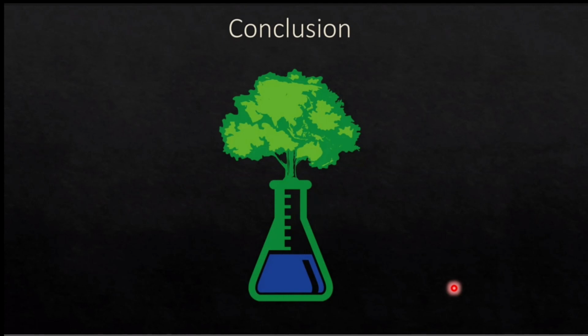So thermodynamically, the red polymorph should be the end all be all of all of these, because it is the lowest in energy. But we did have one very interesting result from an experiment that we really weren't able to replicate. We didn't go too far down this road. But what we found is that over time, some of our samples did end up with a yellow dust on them when they were exposed to air for a long period of time. We're pretty sure it's not the red compound that's decomposing, but it may be that there's amorphous orange polymorph in there, and that orange polymorph may have some pathway to get to the yellow more easily than we assume. So there could be something going on there.